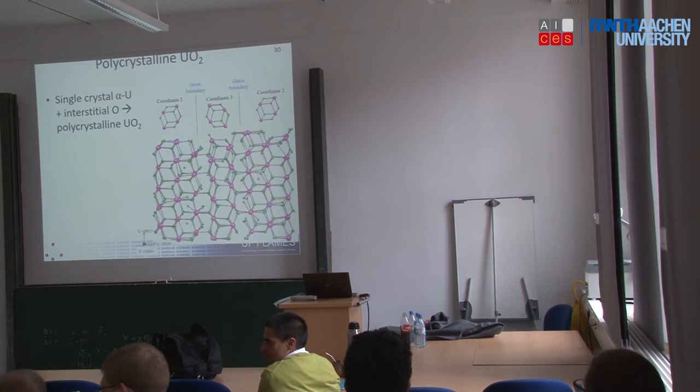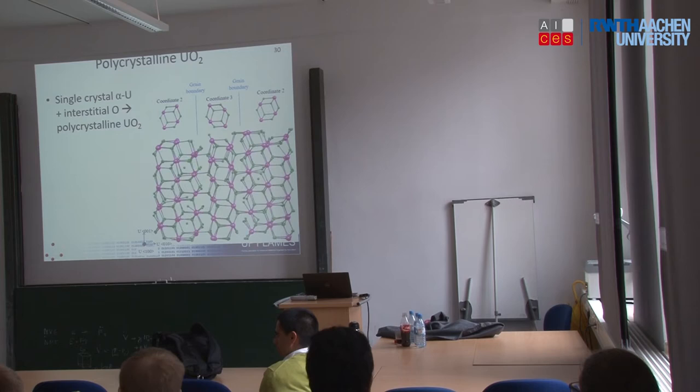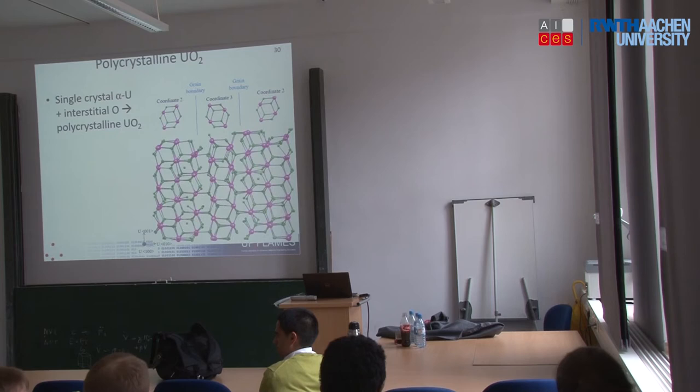Now, our charges are not necessarily matching up with experimental values of charge, and that's not unusual. If you look at the fixed charge potentials for ionics, for example, there are potentials for silica which have silicon as 4+, and potentials that have silicon as 2.4+. That difference is compensated for somewhere else in the potential. But broadly speaking, things which are more charged here are physically more charged. The rough order is about right. I don't know of any real absurdities where we get positively charged oxygens or anything like that. We've never seen those kinds of situations.